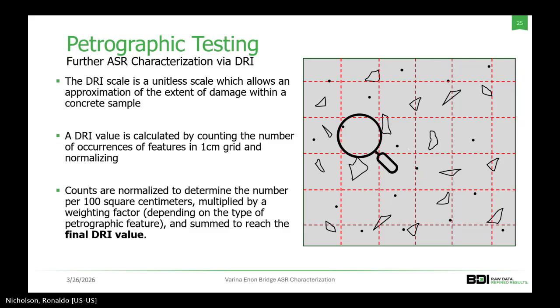So in order to further characterize the ASR, we also performed this calculation of a DRI value. DRI is a unitless scale which allows an approximation of the extent of damage within a concrete sample. It's calculated by counting the number of occurrences or features in a 1 centimeter grid, and then normalizing it to determine a number per 100 square centimeters multiplied by a weight factor depending on the type of feature. And then this is summed up to reach a final DRI value. So this is a process, again, to further characterize ASR based on specific features such as cracking in and around the aggregate, that kind of stuff, of a concrete.